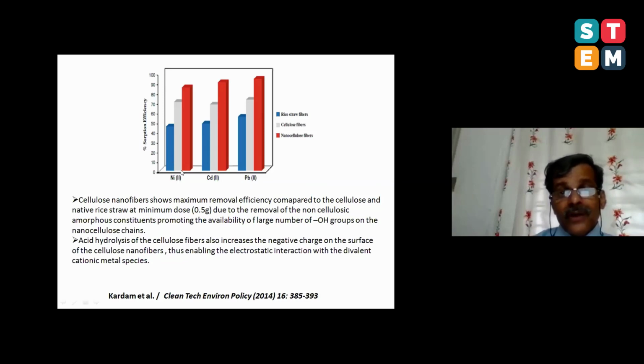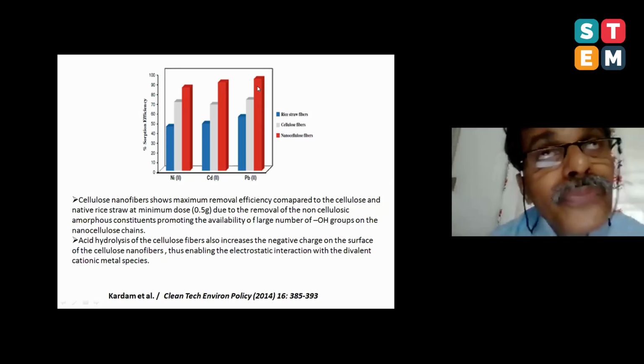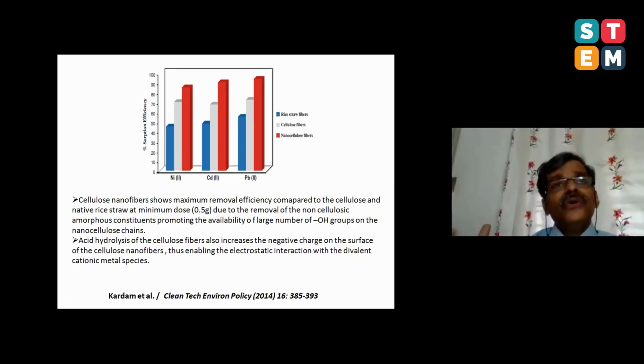If you use raw fibers, rice straw fiber, you can see removal of nickel. We are comparing three systems: rice straw fiber, cellulose fiber, and nanocellulose fiber. Look, removal of nickel is very efficient when you go to nanoscale. Removal of cadmium becomes very efficient when you go to nanoscale. So this is raw straw fiber, this is the microcellulose, and this is nanocellulose. Look at lead. The removal efficiency is very high when you go to nanoscale. So my summary is, if you use nanocellulose, you can trap many of the heavy metals.